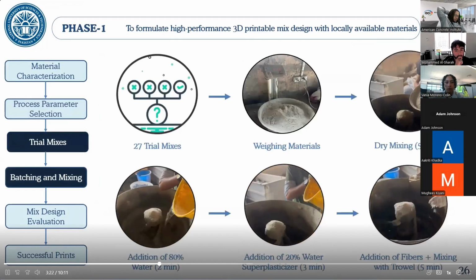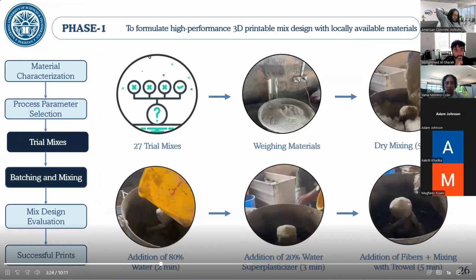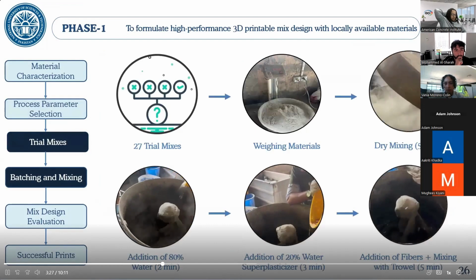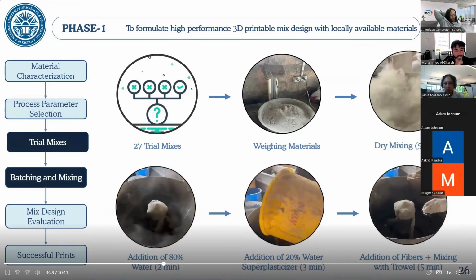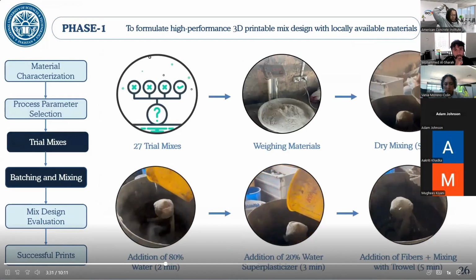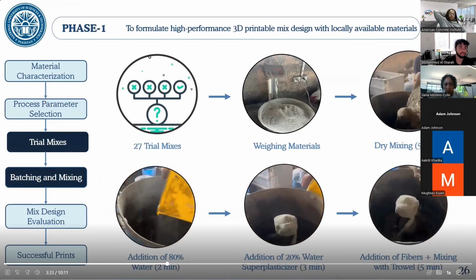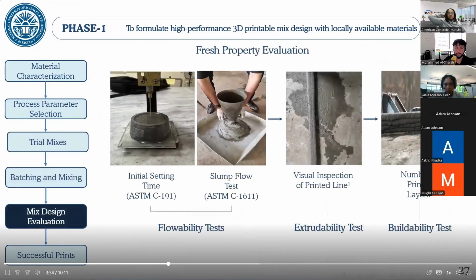So this is the mix design which we developed for the smooth flowable mix. And in this phase, we tried a total of 27 mixes, out of which we chose a representative 8, which I'll shortly discuss. So coming over to evaluation of our mixes, first we looked at the fresh properties. For the flowability, initial setting time and slump flow tests were performed, while extrudability and buildability were inspected visually.